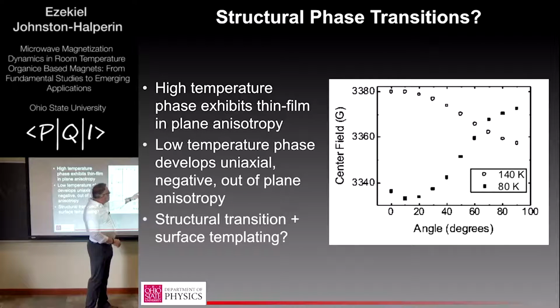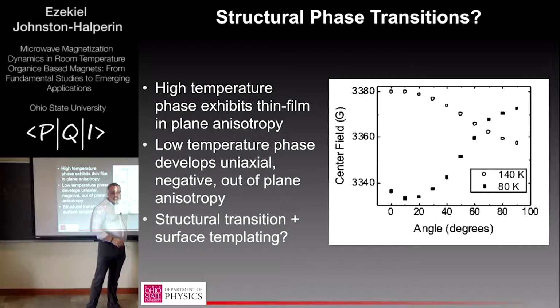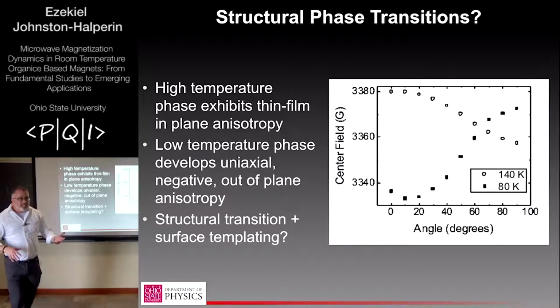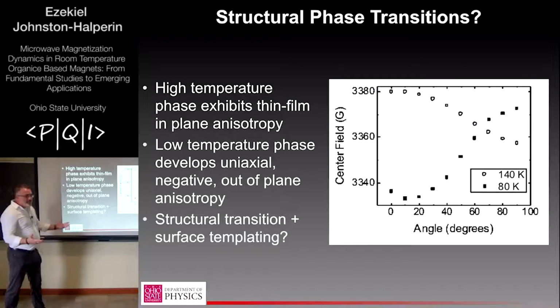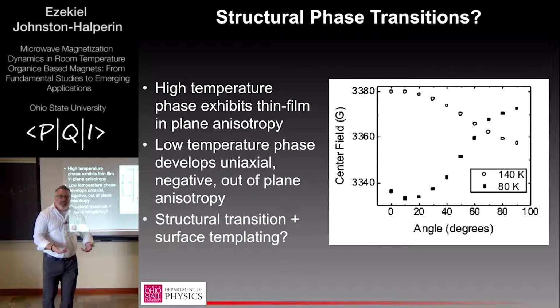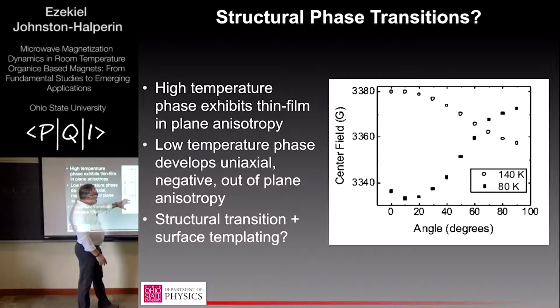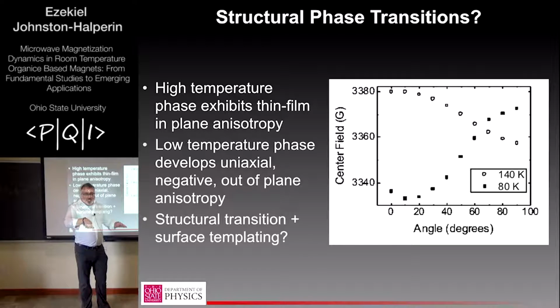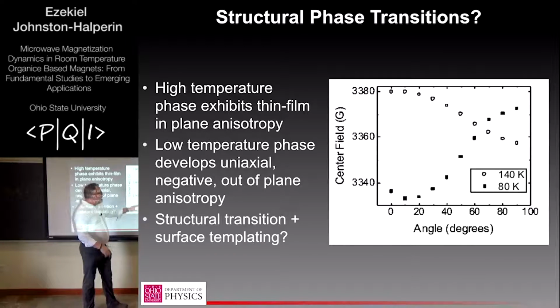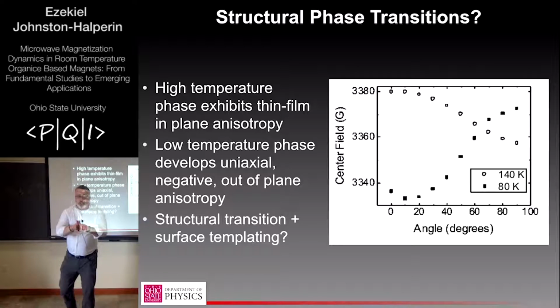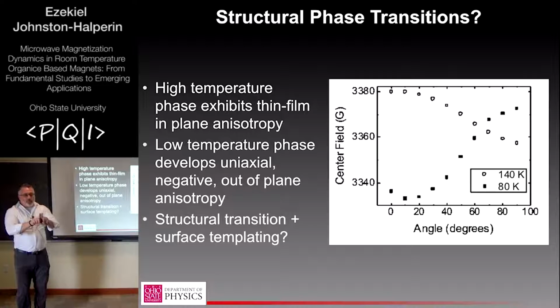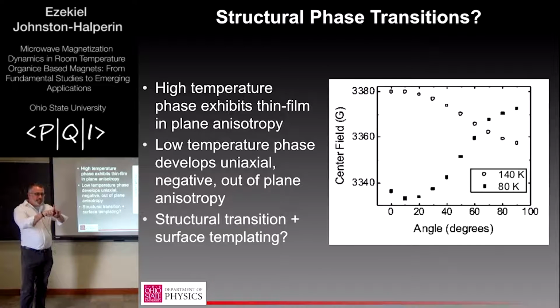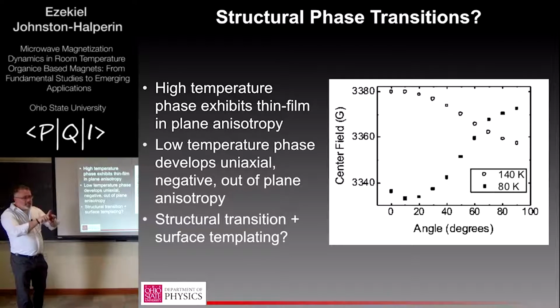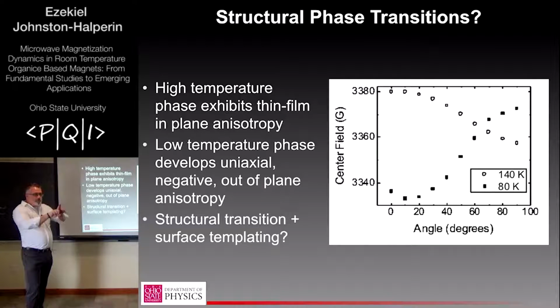And in fact, because it goes through zero, we can say the sign of this crystal field anisotropy is negative. In order to have a crystal field anisotropy, you have to have some crystalline order. So this is further evidence that, and now this is not the in-plane rotation I was talking about with nanowires, this is all in-plane to out-of-plane. This is another way of pulling out the degeneracy that I mentioned before. With the nanowires, we're effectively rotating one of these anisotropies to in-plane so that we can detect it. Here, they're still both pointed in this direction at high temperature, and at low temperature, one of them flips.